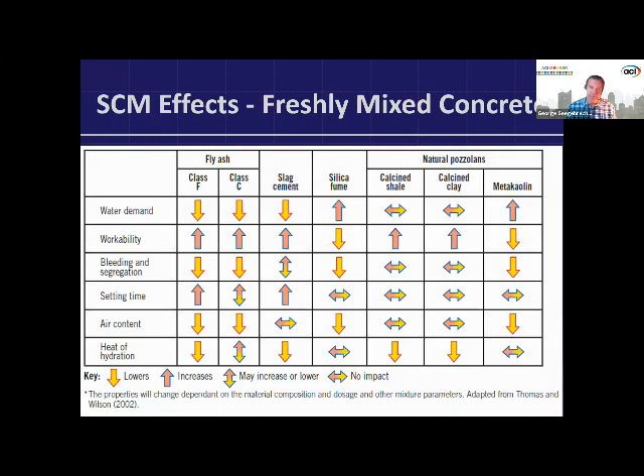Then this graph from PCA, Design and Control of Concrete, summarizes the effects of those. From that previous list, I'm only talking about the F and C type fly ash, the slag, and the silica fume, which are the most common ones used. For setting time, fly ash type F increases setting time. C has a dual effect, increasing or decreasing based on the dosage and its chemistry. Slag increases setting time, and silica fume really doesn't affect it at all.